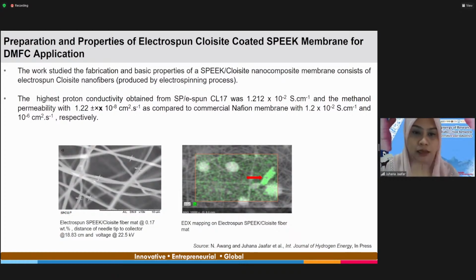This is the same image showing our Cloisite nanofiber. This is not yet the membrane, but the nanofiber, the Cloisite nanofiber. And we do doping. The silicon element in the nanofiber proves that we managed to electrospin Cloisite clay. And you can see the dispersion of the Cloisite in the nanofiber is uniform, with just a small part of agglomeration here, but more or less we managed to get the uniform distribution of the Cloisite in the nanofiber.